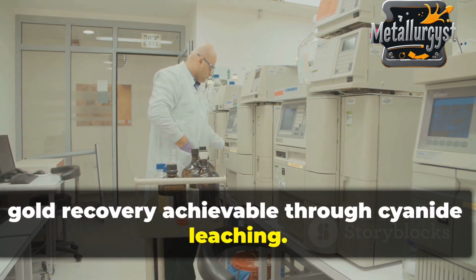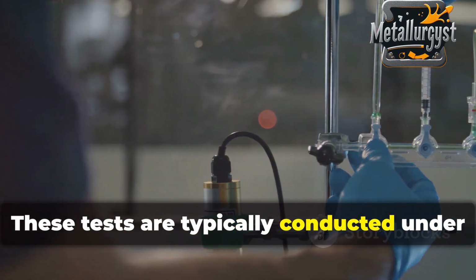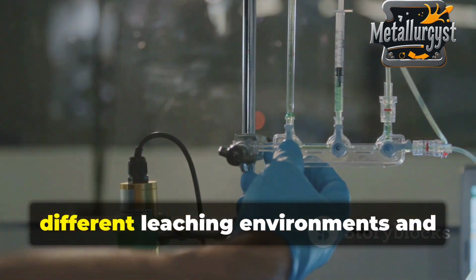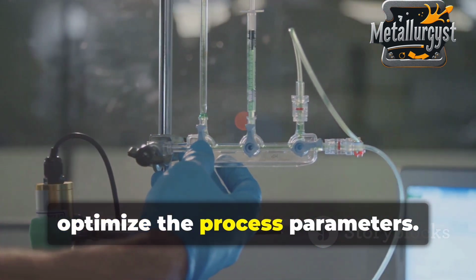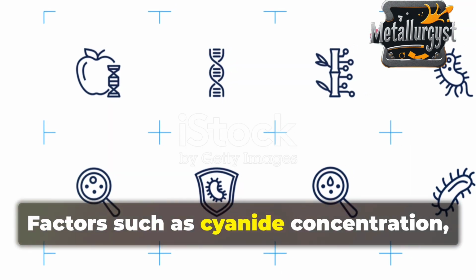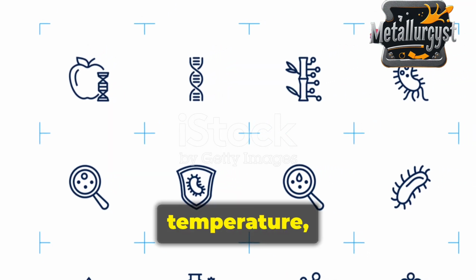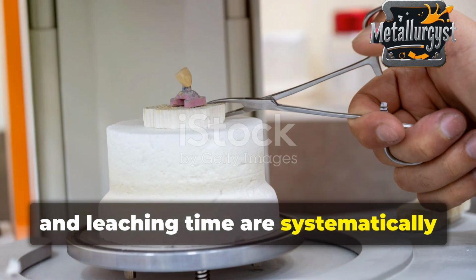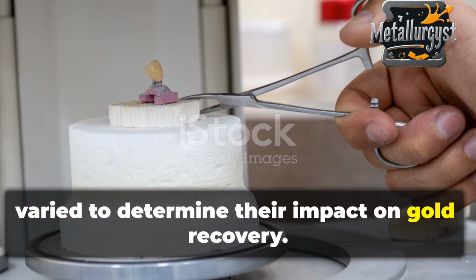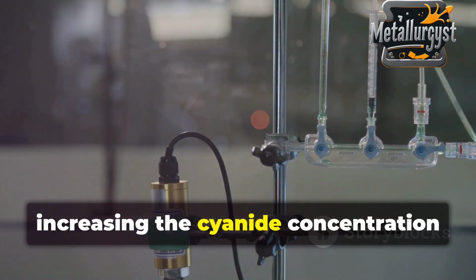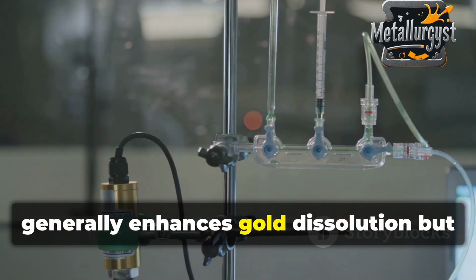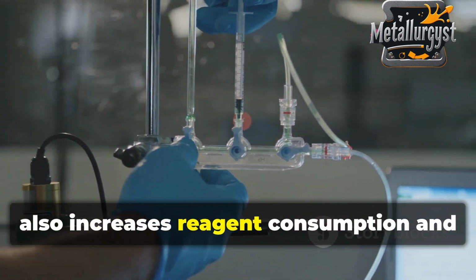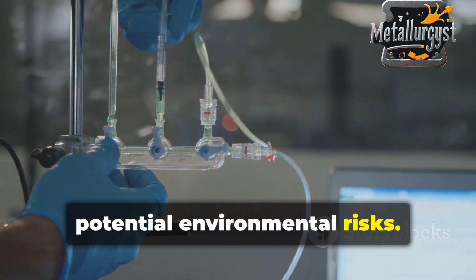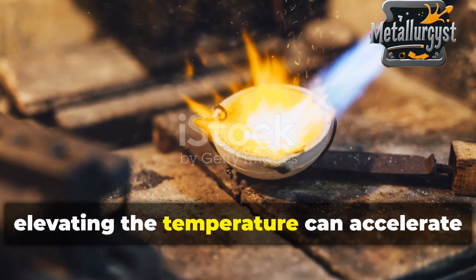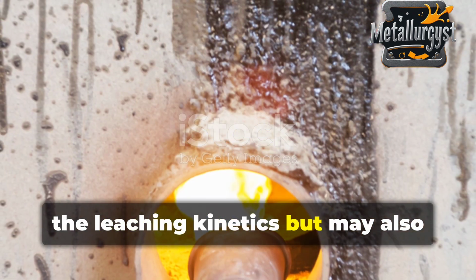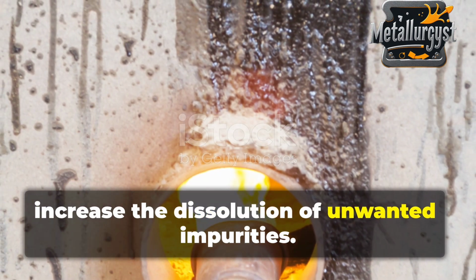through cyanide leaching. These tests are typically conducted under a range of conditions to simulate different leaching environments and optimize the process parameters. Factors such as cyanide concentration, pH, temperature, and leaching time are systematically varied to determine their impact on gold recovery. For instance, increasing the cyanide concentration generally enhances gold dissolution, but also increases reagent consumption and potential environmental risks. Similarly, elevating the temperature can accelerate the leaching kinetics, but may also increase the dissolution of unwanted impurities.